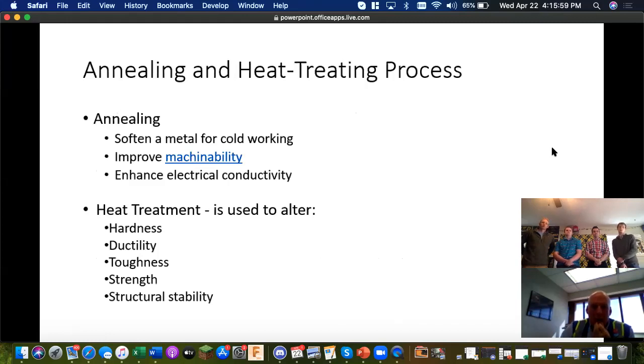So another process previously mentioned is annealing and heat treating. The benefits of annealing are that it softens the metal for cold working and prevents hardening and stress fractures, which improves the machinability. It'll also enhance the electrical conductivity, but in our case, it seems very important due to the stress fracture breaks the first time Horton tried to make a spun metal pulley. So we would highly recommend annealing during the process. When the whole process is over, you can heat treat it to increase the hardness, lower the ductility, increase the toughness and strength, which will overall just increase the structural stability and the longevity of the part.